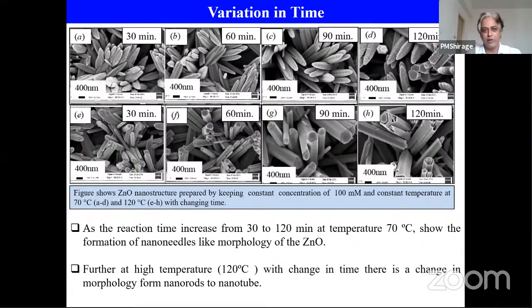In order to check this time, I have utilized two temperatures. For example, in these four images, A, B, C, D, I utilized temperature 70 degree, and the remaining images E, F, G, H were prepared at 120 degrees centigrade. This is also very clear that time plays a very crucial role: 30 minutes, 60 minutes, 90 minutes, 120 minutes. With this, the rod-like morphology changes to tube-like morphology. It means that all three parameters play a very crucial role. So when we prepare the material, it's very important to control concentration, time, and temperature of the synthesis very carefully, so that we can get the very good morphology, whatever you desire for your material.